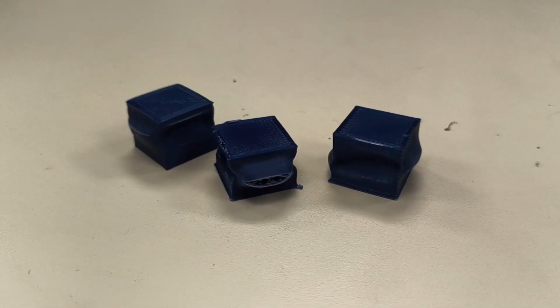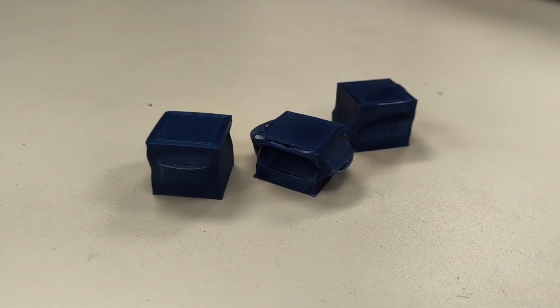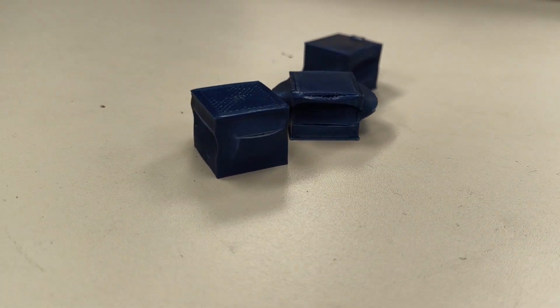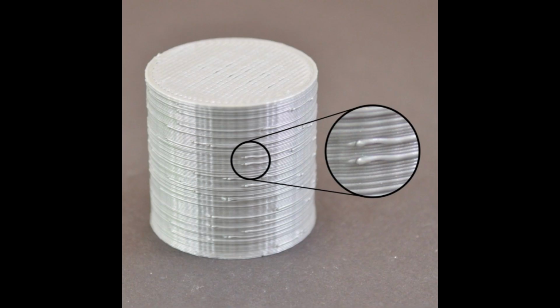A major weakness of our experiment is that 3D printers can produce defects in the print itself, including layer shifting, bed warping, and/or surface defects as seen in the image above. This leads to forces accumulating in these defects, which can lead to premature failure.